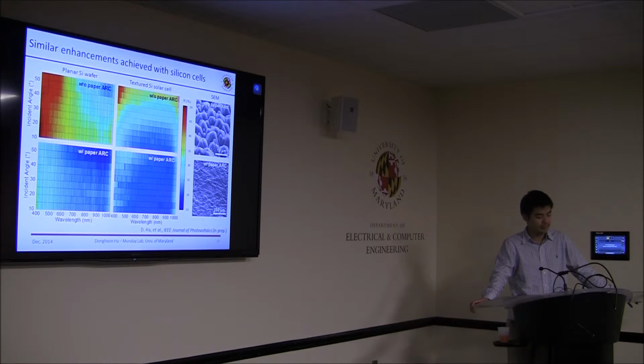So we wanted to apply this paper ARC to other types of solar cells. One is planar silicon, and the other is textured silicon. On the planar silicon wafer, as expected, the measured reflectivity has been reduced, similar to gallium arsenide. For the textured cell, because the surface has textured configurations, it already has even better optical properties compared to the planar type of cells. However, even on that surface, our paper ARC can further minimize the reflectance, as shown in the contour plot.